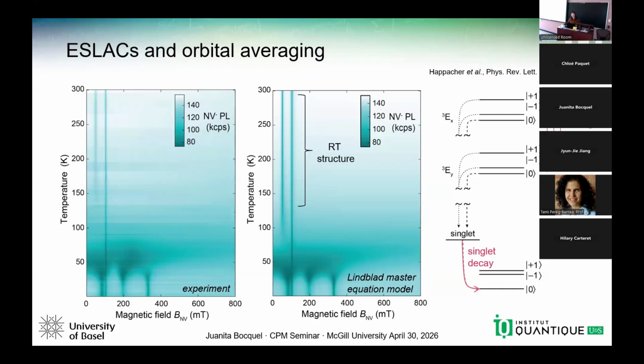Sorry, what kind of phonons are the main ones in the mixing case? Things like acoustic phonons, and it's a two phonon driven process. It has this T to the 5 scaling with temperature. Yes. Yeah.